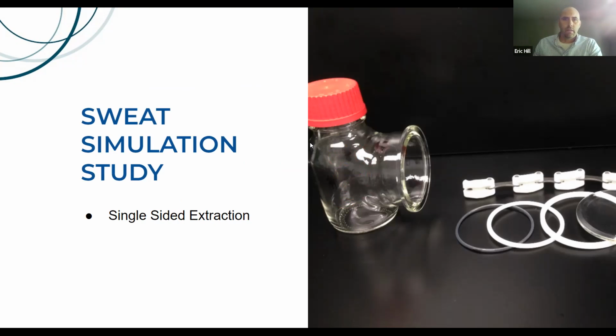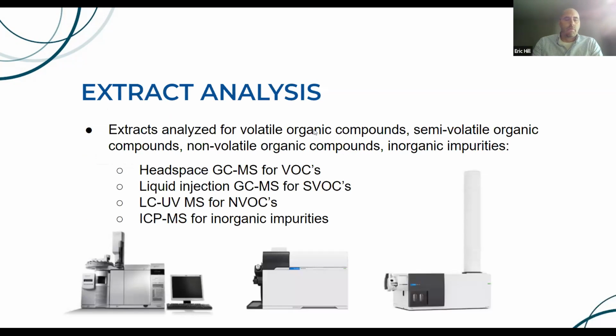Okay. And then from there, once we generate those extracts, whether it's the solvent extracts or the sweat simulated solvent extracts, we're going to go into extract analysis. And the extracts are analyzed for volatile organic compounds, semi-volatile organic compounds, non-volatile organic compounds, and inorganic impurities. We're going to utilize headspace GCMS for the VOCs, liquid injection GCMS for the SVOCs, LC-UV-MS for NVOCs, and then ICP-MS for the inorganic impurities.